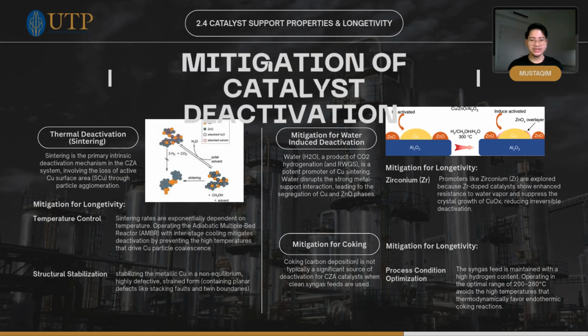The second one is water-induced deactivation. Water is the product of methanol synthesis and acts as a potent promoter of copper sintering, disrupting the strong metal-support interaction. Future material design must address this by integrating highly stable structural promoters such as zirconium. Lastly, carbon deposition or coking is generally not a significant issue in the system, provided we maintain a clean syngas feed with a high hydrogen content.